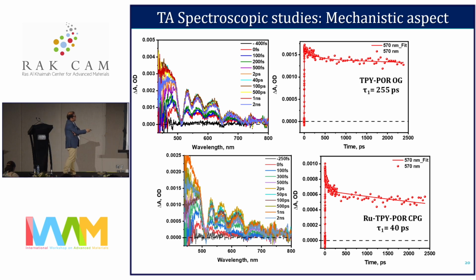You can see the relaxation process, from the first relaxation process, it skips for particularly the organogel, T1 is 255 picoseconds. But when you have the coordination in presence of ruthenium, the first component, T1, is very, very fast, that is 40 picoseconds. This means that the electron migration is happening from the porphyrin system to the ruthenium system. So that first electron transfer is helping for this catalysis.